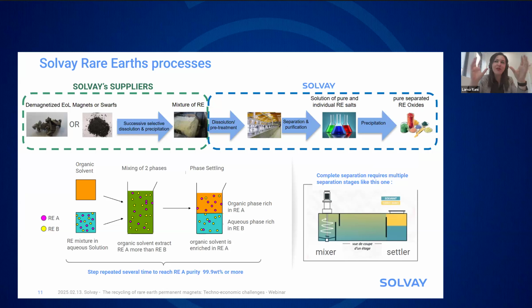For the long loop recycling, we said that the magnet powder, after collect, dismantling, and making the magnet powder or swarf, will go into a leaching step. So this is what we call the hydrometallurgy step. This part of the process from collect up to the production of a mixture of rare earths, let's say free of iron and boron and free of many impurities by successive selective dissolution and precipitation steps, is led by Solvay's supplier, and we were very happy to announce the collaboration we have with Cyclic on that and on this supply.